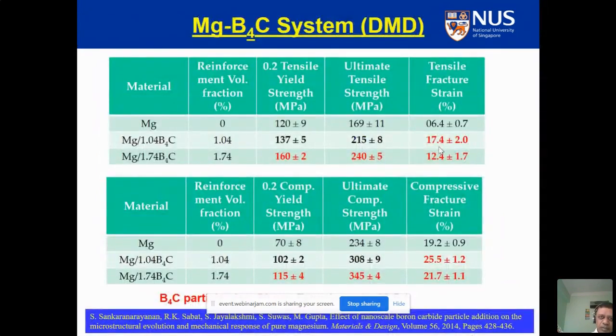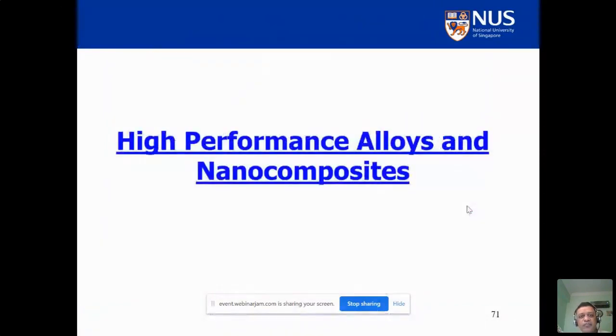Now let's have a look at the ceramic reinforcement such as boron carbide. And once again, you see that in the top table, with 1.74% of boron carbide, you are able to increase the yield strength, UTS, and your ductility becomes double. If you want to triple the ductility, just put about 1% boron carbide and you can have wonderful ductility, not only under the tensile loading, but also in the compressive loading, you're able to increase the strength without compromising on the ductility. And that is once again the beauty of nano size reinforcement.